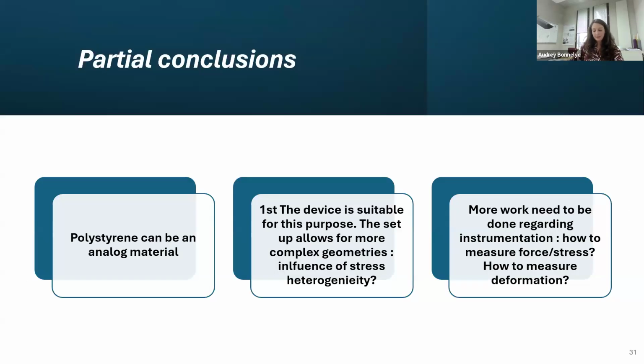And so this is leading me to my partial conclusions. I think that polystyrene can be an analog material, and I'm very happy of that because it means that we can use that to calibrate our machine and to test many parameters. The device is actually suitable for this purpose, and it's good because it was not designed for that. And it means that we can go for more complex geometries than what was done in the past, and look at the influence of stress heterogeneity, for instance, or various stress orientations, because we are under true triaxial conditions.